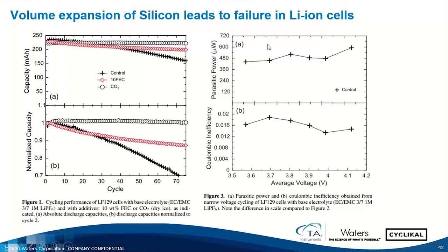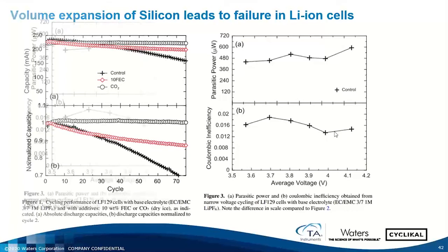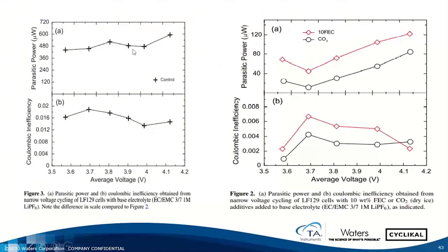This is the thermal power signal from just the control. And you can see, as we're using our integration subtraction technique and examining the state of charge up around the top of charge, 4.15 volts or so, we're up around 600 microwatts of parasitic thermal power, and that's supported by the Coulombic inefficiency. I want to show you that same data on this slide. Here is the parasitic thermal power from the control and the Coulombic inefficiency. I had to put this on different plots because of the change in scale.